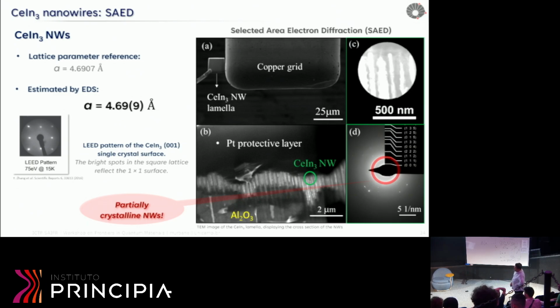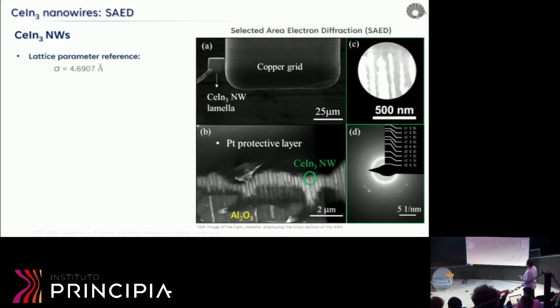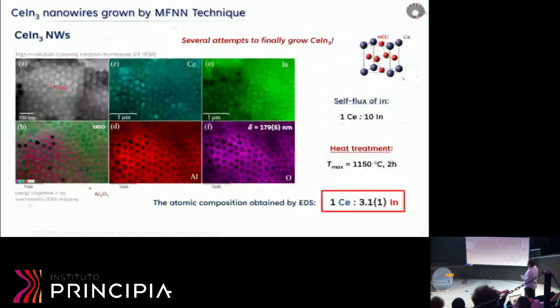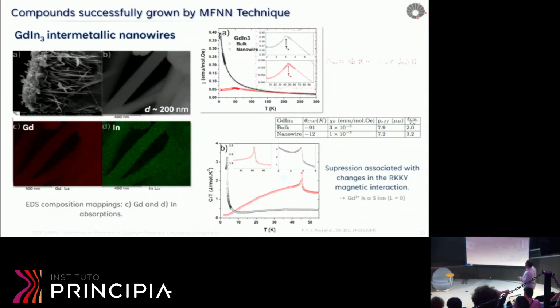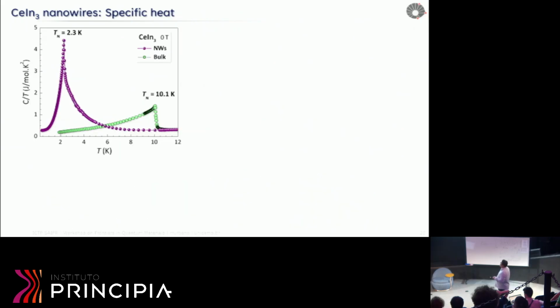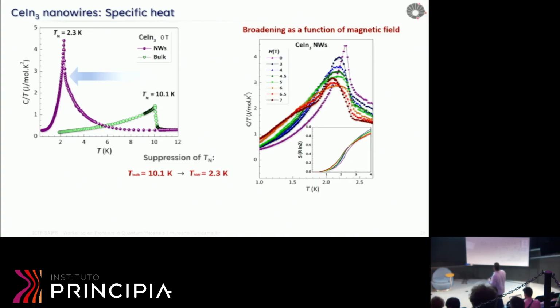Ricardo, in your heat capacity curves, you first showed us a heat capacity curve, and you said, okay, this one is a little bit higher because it includes the contributions from the aluminum templates, right? Yeah. And later you showed us an evaluation of the entropy. You're comparing this one with log 2, right? Yeah, log 2 because the ground state is a doublet, Gamma 7.